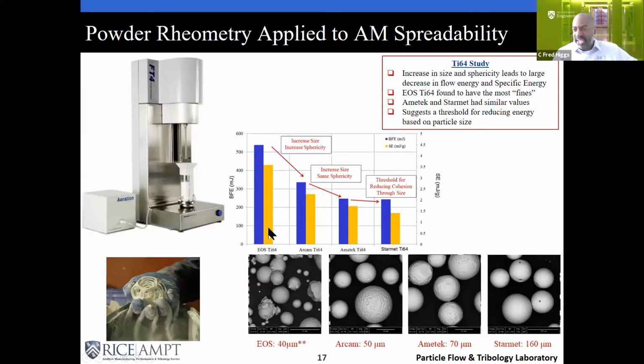And Rob can tell you something about surface area to volume ratio. If you're increasing the size of the particles, the forces between the particles are going to decrease. The surface force is going to decrease. And that's showing up in this energy parameter here. Also increasing the sphericity: if it's more aspherical, imperfectly spherical, then now you're going to have less contact. It's going to be less energy there. And then at a certain point, you get big enough, you reach a threshold where there's no cohesion anymore. So there's less energy when you're doing that.